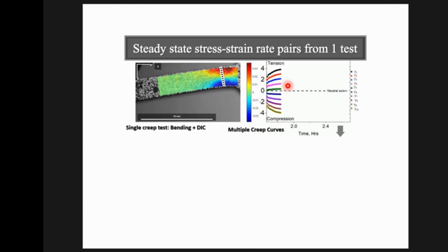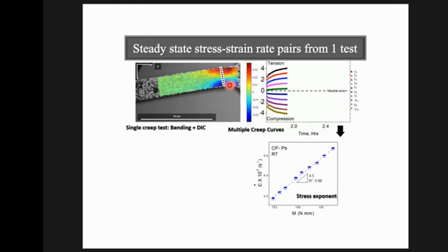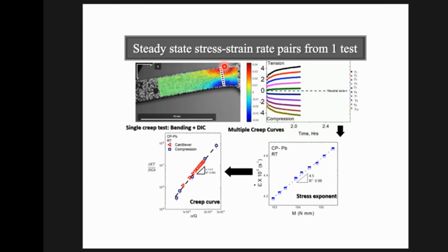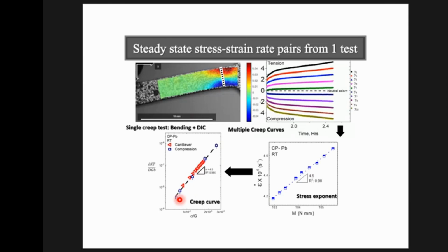And once you reach steady state, you're acquiring multiple data points across the cross-section here, always orthogonal to the curvature. And you're able to get multiple stress strain rate curves. And if you superimpose the red ones which come from the cantilever on the other ones, which are either blue or black, I can't tell, which come from individual uniaxial experiments, you'll see that you recover the same data. So this is a way of using a cantilever which is all said and done easier to align. You can cut smaller samples and replace multiple tests with one of them.